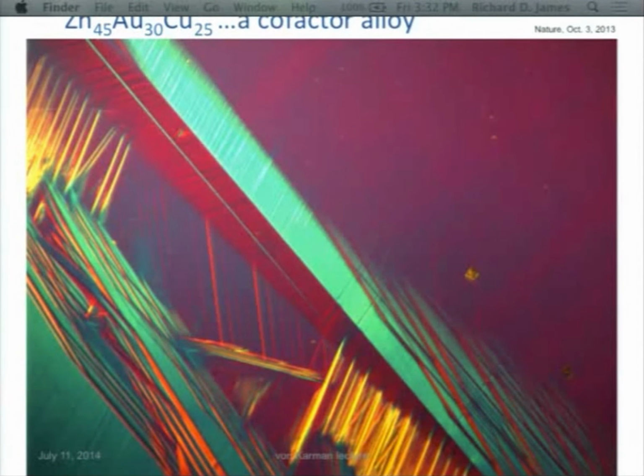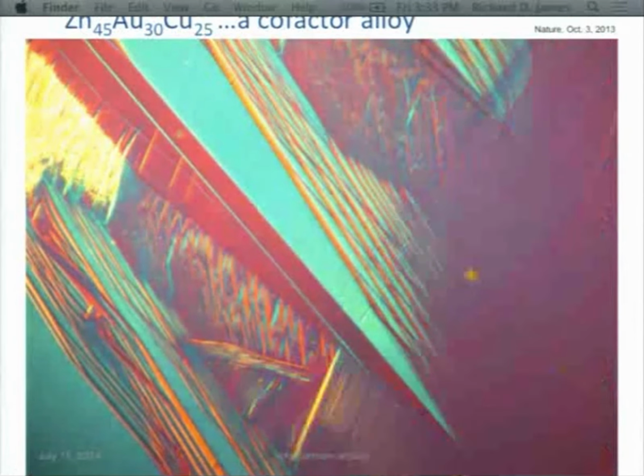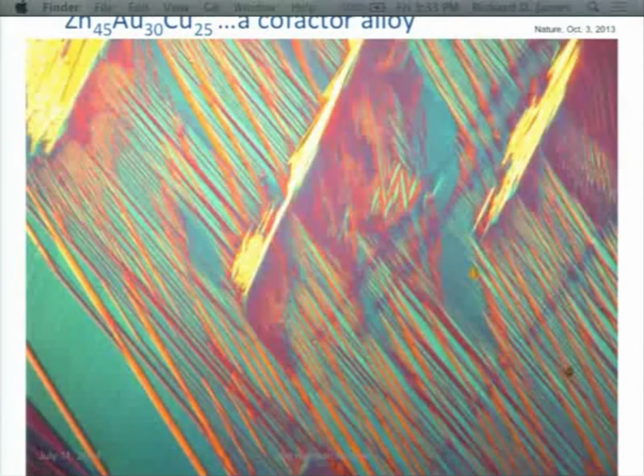So I'll finish my talk by showing you this zinc, gold, copper alloy, which has been tuned to satisfy these very strong conditions of compatibility. I should warn you, you may not have seen many martensites in your life, but it is unlike any martensite that I have ever seen. So this is just heating and cooling the crystal. In fact, it's a polycrystal, looking at one grain in a polycrystal. And the most remarkable thing is every picture is completely different. There are microstructures here, like curved interfaces that we've never seen in phase transformations before. And it has about 1 degree hysteresis. So we hope that can open up the way to highly reversible phase transformations.